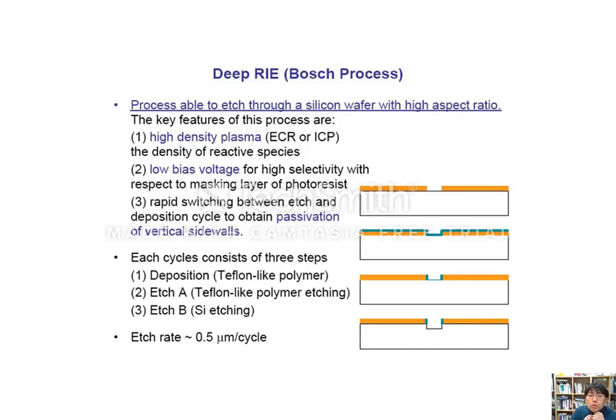Okay, but when we use this machine, particularly, you can buy a machine called ICP or ECR. This kind of machine you need for the deep etch process. The key features of this process are you need a high density plasma, and then you need a low bias voltage for high selectivity with respect to the masking layer of photoresist. And then rapid switching between the etch and deposition cycle to obtain the passivation of the vertical sidewall.